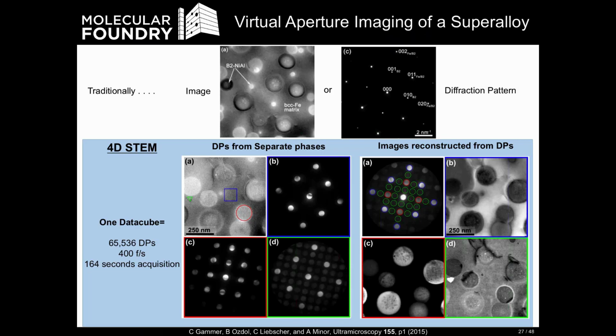On the right-hand side, Christoph has shown green circles, red circles, and blue circles corresponding to the various unique or shared diffraction points. If you simply sum up all of the pixels in diffraction space for each probe position, you can then form a virtual image from those diffracted spots. That's shown in B, C, and D on the right-hand side as the blue, the red, and the green circles respectively. So this is a single experiment, and we more or less collected all of the local diffraction patterns, the local selected area diffraction patterns, for each individual probe on this grid of 256 by 256 probe positions. This is an example of how you can collect a single data set and perform many, many different experiments with it.